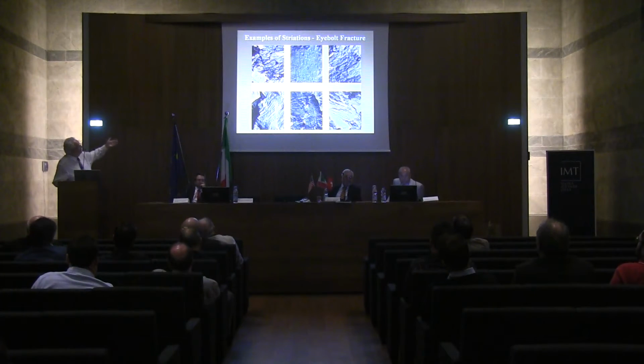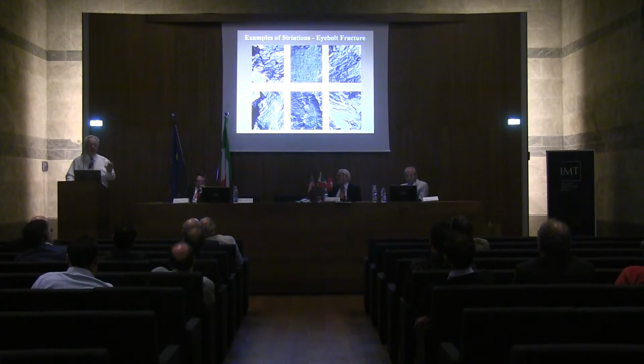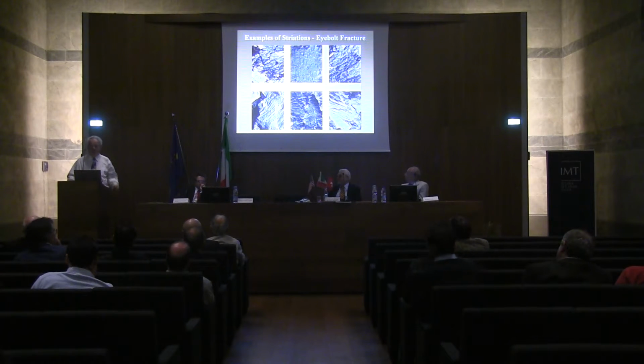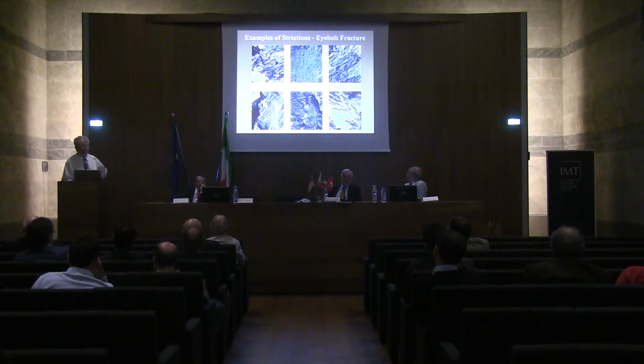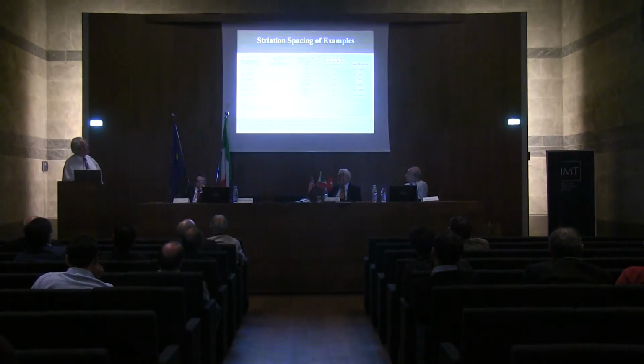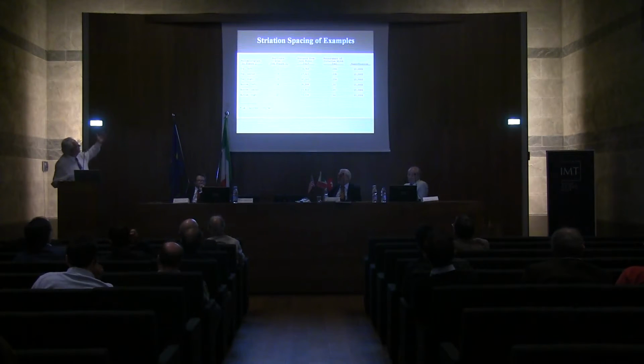So these are examples of the striations that I could see in the different locations. Now, you have to be very careful because you can have fracture through the pearlite colonies, and you're going to see parallel lines that are very nice and uniform. That is the interlamellar spacing of the pearlite and has nothing to do with the fatigue crack growth. So you've got to be careful that you don't actually measure the interlamellar spacing while you're trying to measure the striation spacing, and that can happen. So here's some data that I got from these different pictures that were just shown a minute ago. The replicated areas.